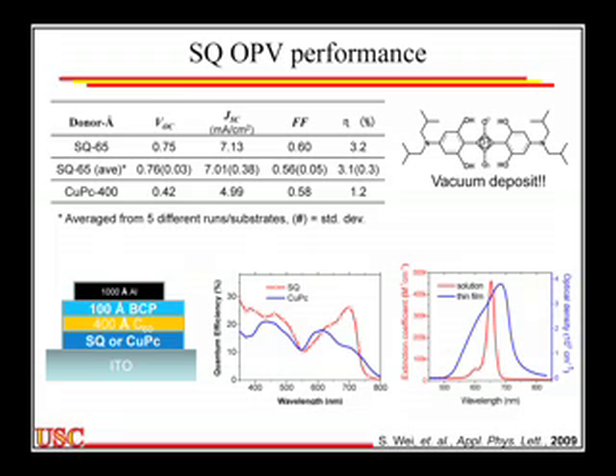We weren't the first people to make devices. We actually got scooped by Tobin Marks' group at Northwestern. They made some devices with this particular derivative where they were pushing to try to get out into the near infrared. These are bulk heterojunction devices. Oh, and I lost the legend. These are 4 different devices. This blue trace is the one I listed here. It's the best device that they had, which has an efficiency of about 1.2%.